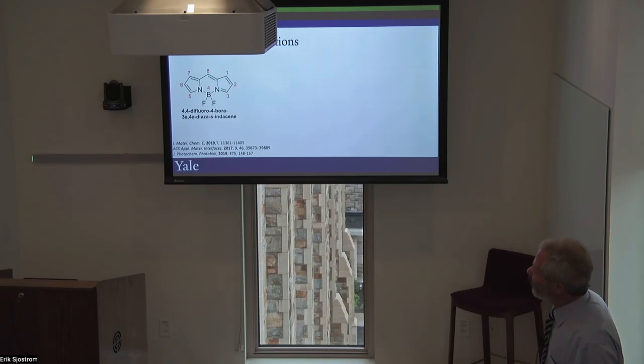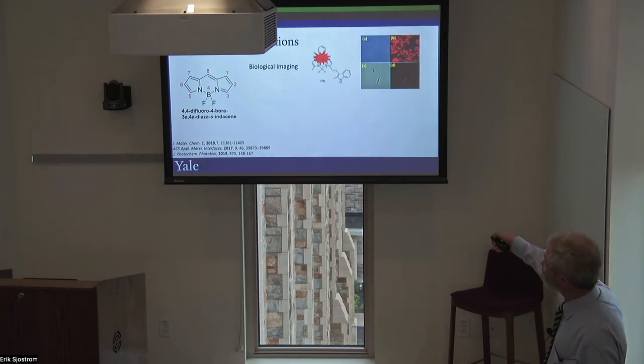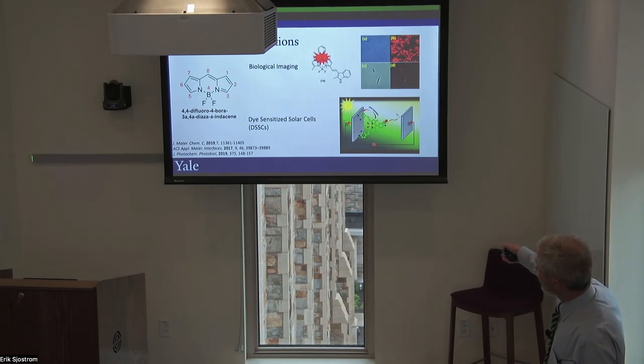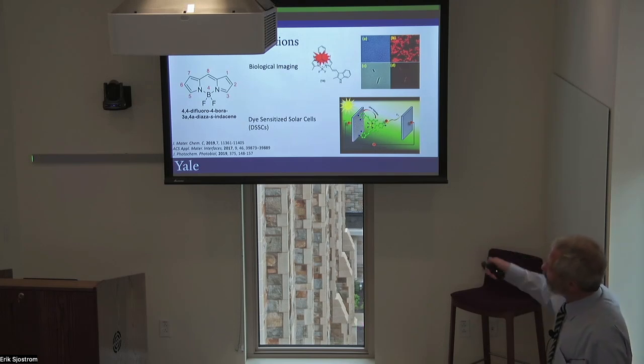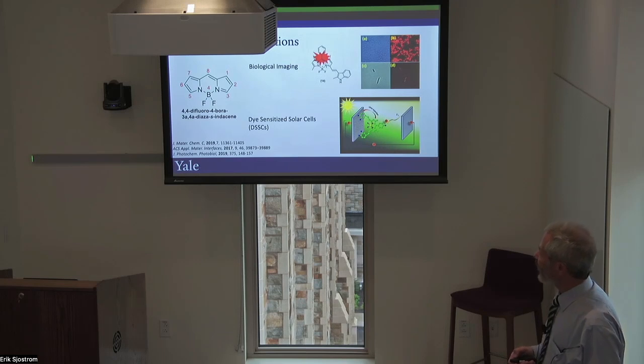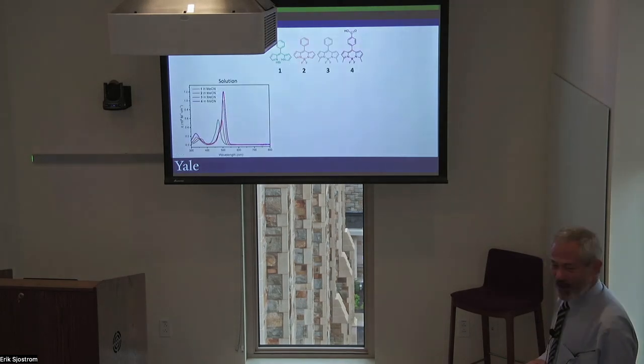But more recently, we started looking at this molecule here. This is called BODIPY. It's a dipyrrin molecule, but it's got this boron difluoride group. And it's been very widely used in many applications, including biological imaging. It's a very highly fluorescent molecule. It's been used to image biological systems. And it's also been used in solar cells. In this case, however, by putting on an anchoring group, here's the attached anchoring group, and you can see here is the boron difluoride group. And we were pursuing this because we thought it might have interesting light absorbing properties. But to our surprise, it loads spontaneously onto the surface and binds to the surface of titanium oxide.